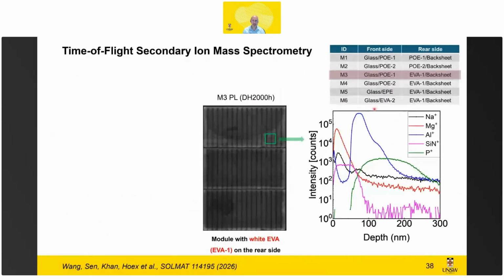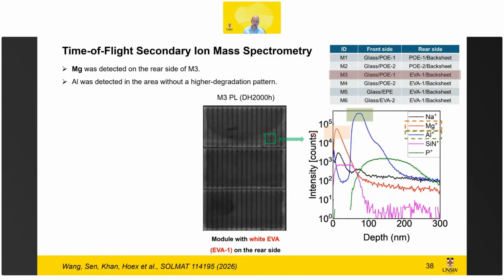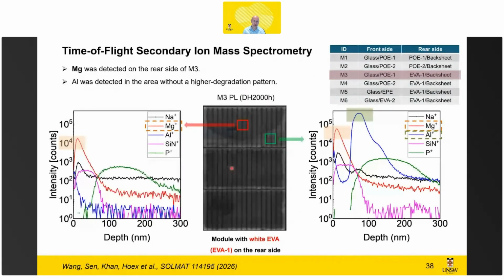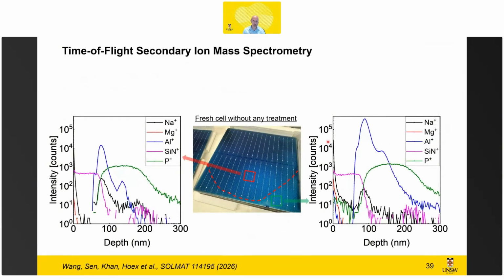So we investigated, first of all, with time-of-flight SIMS for the cells that had degraded. We had taken them from the module, and we saw significant amounts of magnesium in both the good and the bad part. So that was puzzling at first as well. The cells were cleaned after being taken out of the module, and we ensured they were clean before we did the measurement. So the magnesium we measured really had reacted with the solar cell. And if we looked at the cells before, they did not show any presence of magnesium, so it's at the detection limit.